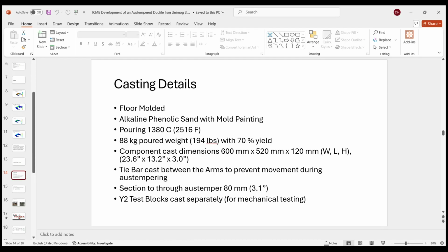And there's a couple of adaptations. For example, we had to apply tie bars in. From the casting, you probably saw you've got these arms that come out. And obviously in heat treatment, those arms will want to move, because as we heat parts up and cool them down very rapidly, they'll want to move to where they feel comfortable. So we have to prevent that. And the way we prevent that is to put it into a tie bar.